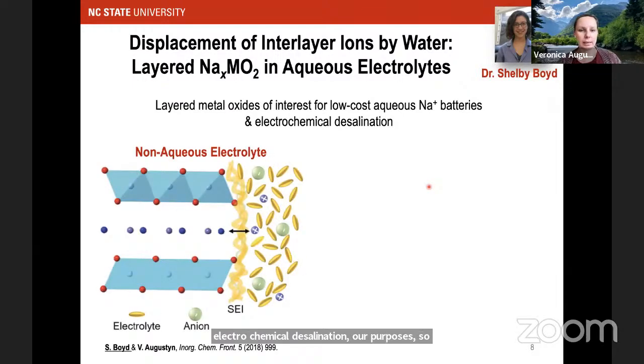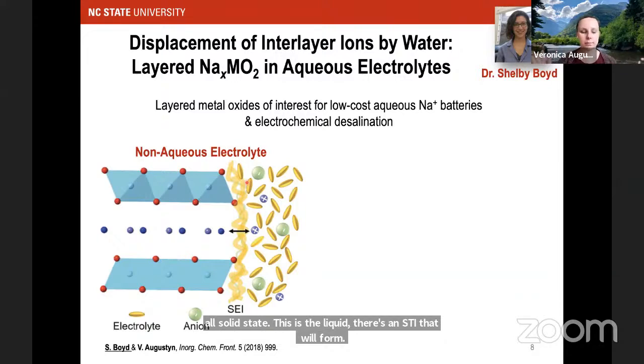So first, in non-aqueous electrolytes, where many of us who study insertion chemistry are raised on non-aqueous electrochemistry, we have this gift in a way where, for most systems, you can assume that what's intercalating into your electrode is a desolvated species. It's a desolvated cation. There's a separation between what's happening in the electrolyte and what's happening in the electrode. This is all solid state. This is the liquid. There's an SEI that will form, but you can think about them as two